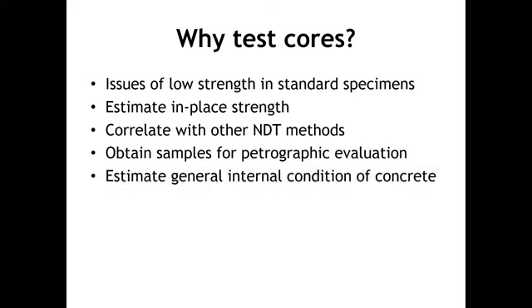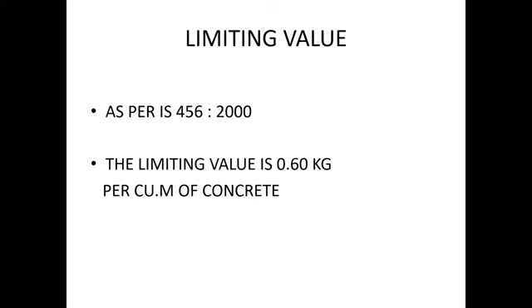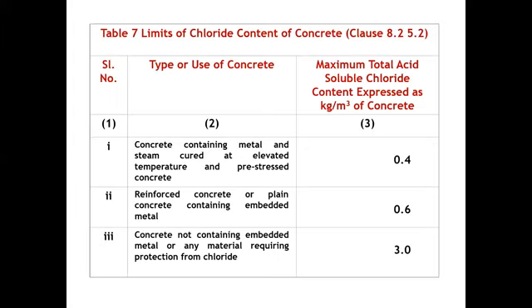And as per IS 456, up to 0.6 kg per cubic meter is allowable, not an issue. That was also well explained by the Professor. Why some amount of initial chloride ion value need not be alarming to the concrete. When it goes beyond that, then you have issues with the chloride. If your pH value is greater than 11.5 and you have very low chloride content, then your structure is not expected to corrode fast.